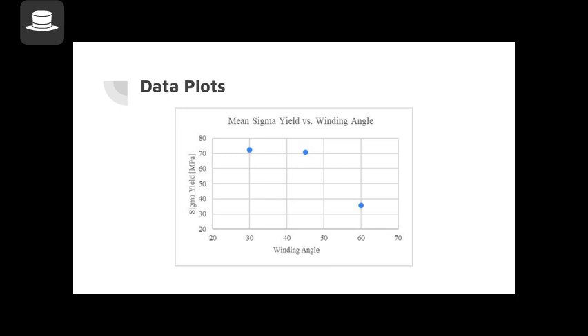Unfortunately, due to manufacturing defects that were discussed in other slides, the 30-degree angle tube had a fairly high standard deviation, and as such, we expect the mean value to actually be much higher. Therefore, we did not do any sort of linear regression or plot analysis to figure out the direct relationship between winding angle and sigma yield as we had initially thought, due to the fact that we think this 30-degree data point is not accurate to what we would expect it to be.